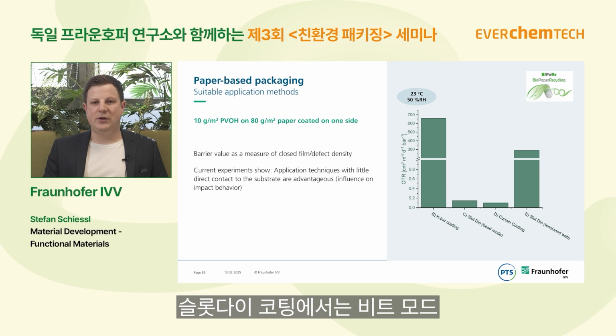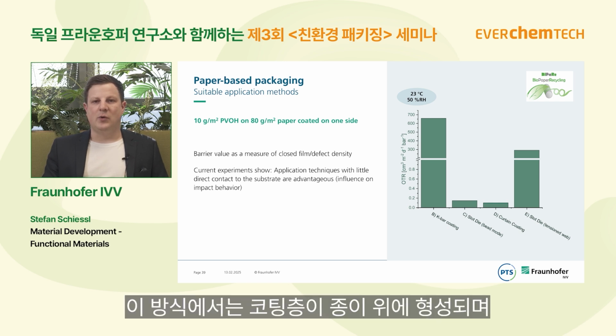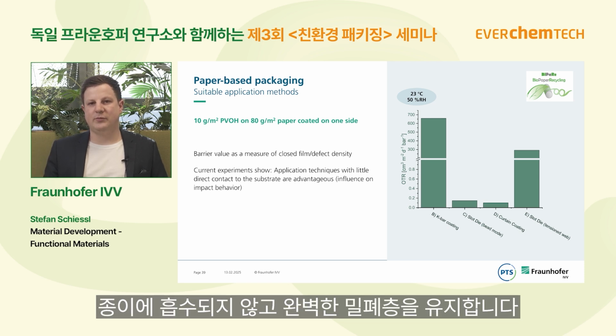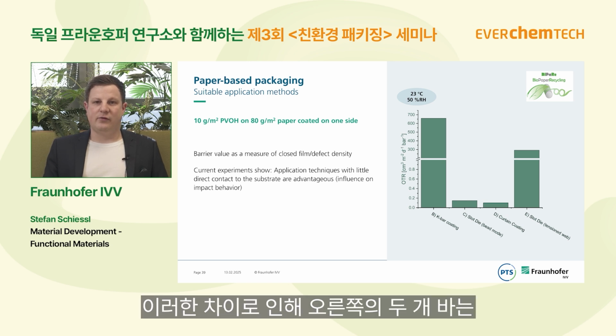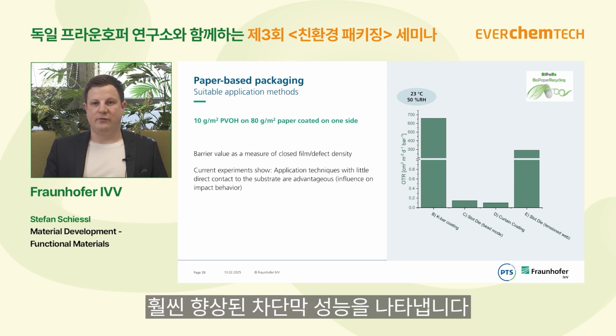in comparison to a coating with slot die, where we can use either the bead mode or the curtain coat mode, where we really lay a layer of the lacquer on top of the paper, which is not pushed into the paper, and building a closed layer really separated from the paper without any suction of the solvent. And therefore we have much better barrier values on the following two bars to the right.